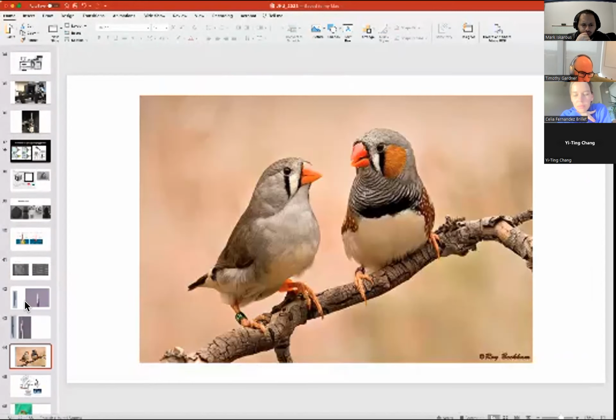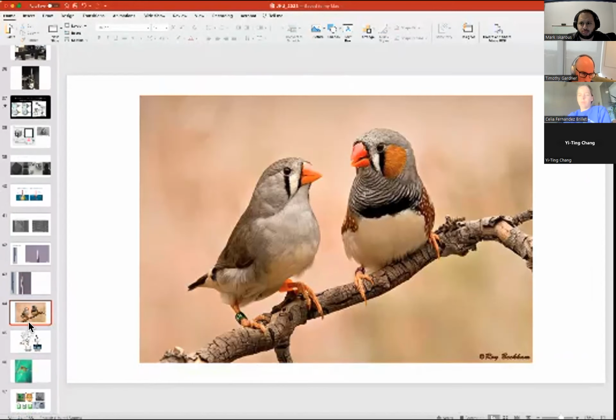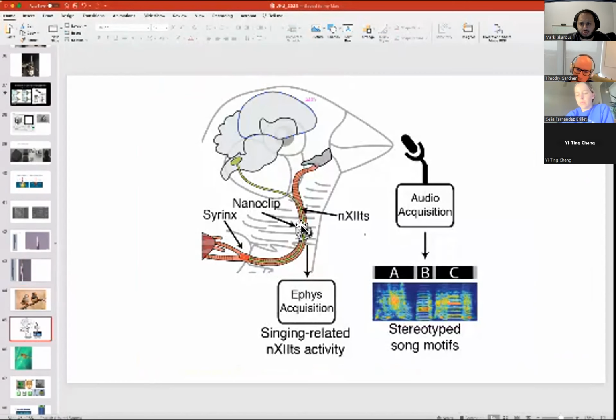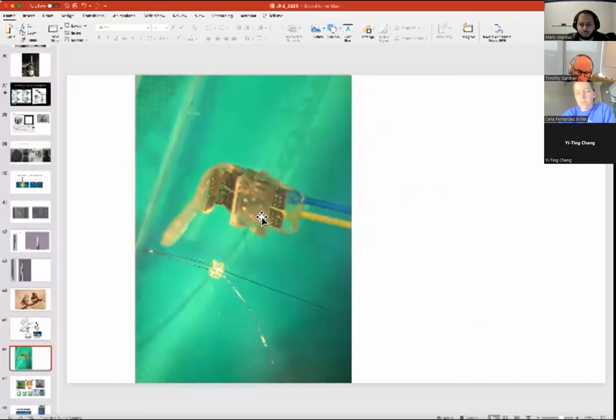All right, so for the Songbird work, the first device that we sought to build with this approach was a nerve stimulator. And so the nerve that drives vocalizations in songbirds is about 150 microns in diameter, really small and fragile. And this, at the time, was the smallest device that we could buy commercially to interface with that small nerve. This is a Cortec 150 micron diameter, or rated for 100 micron diameter nerves. And you can see maybe that interior diameter is 100 microns, but this is the scale of the device that we're able to build with the two-photon lithography, and just much more manageable on a very small nerve in a small animal than this larger bulky structure.